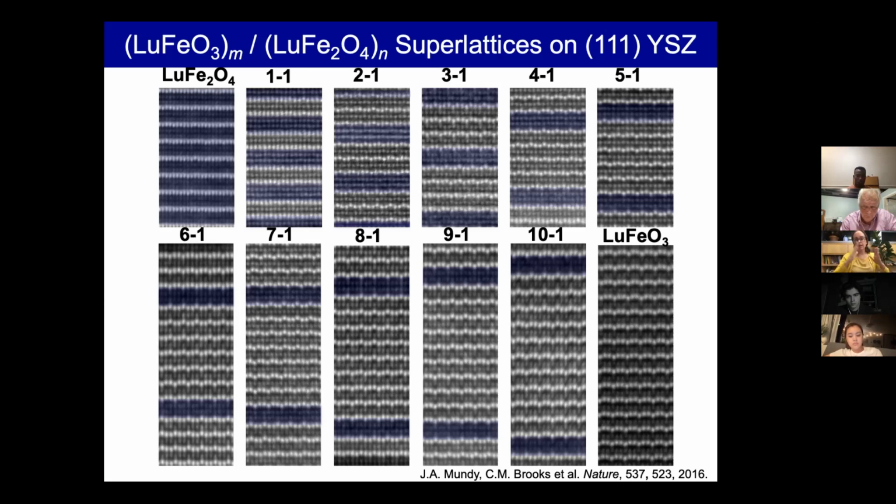So by making these superlattice structures where we layer the materials atom by atom, we were able to interpolate between the rumpling of 40 picometers and not having some of those distortions. We do have some limits on what we can do, but we did find, at least in this system, that it really was a very powerful probe. A lot of physics happened differently with the various levels of rumpling.